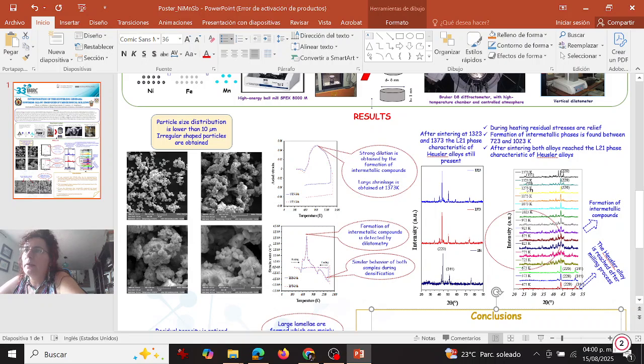In these graphics, obtained with X-ray diffraction, we can observe that after sintering at 1323 to 1373 degrees Kelvin, the L21 phase characteristic of the Heusler alloy is still present, as we can see.